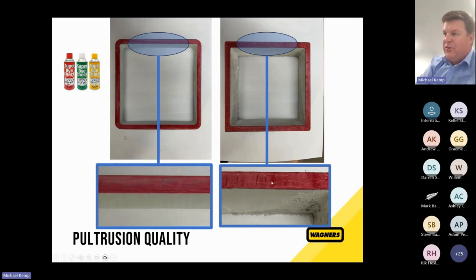And the issues that we see in imported product here are these cracks in the profile, and they're fairly regular. When we process vinylester resins or polyester resins, there is some shrinkage involved, and so compensating for that shrinkage in manufacture is very, very important. If you don't, you will get cracking inside the section. So again, it's an avenue for moisture to get in and to start to cause a problem. It all leads to durability.